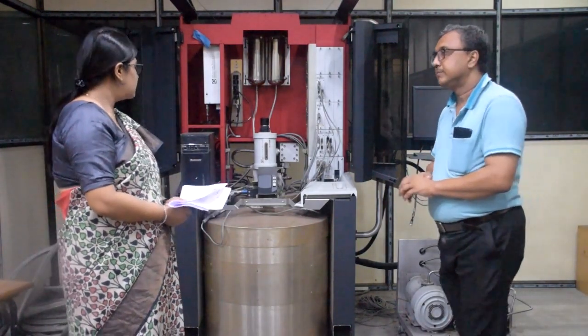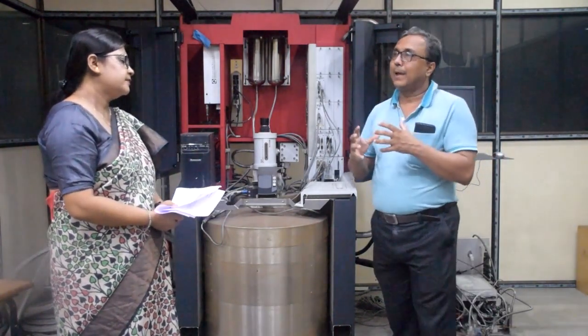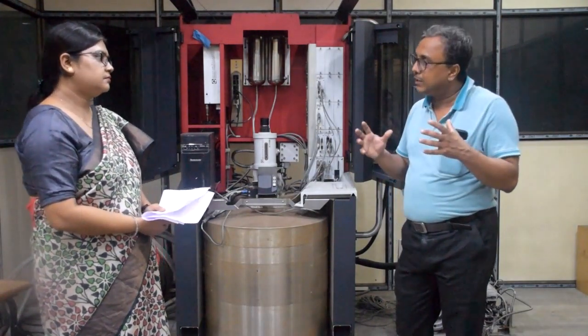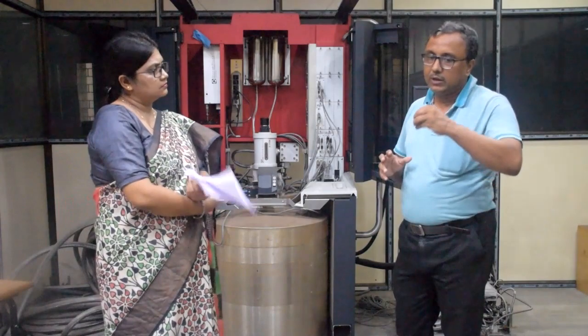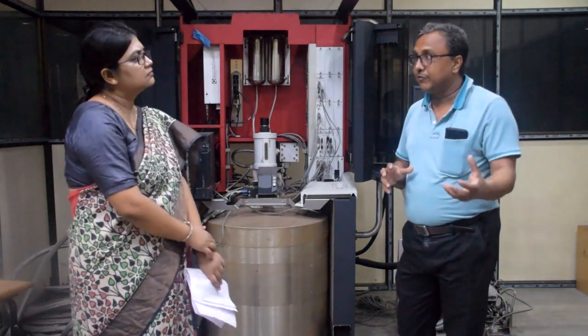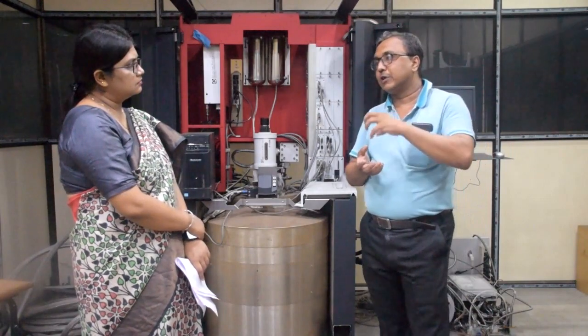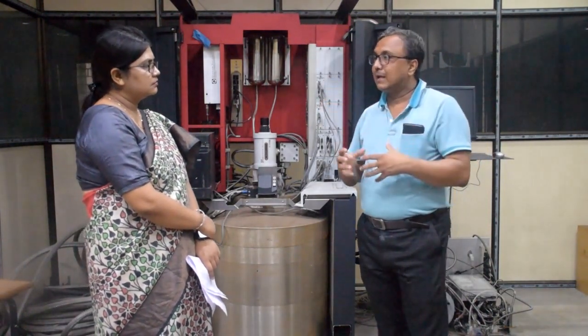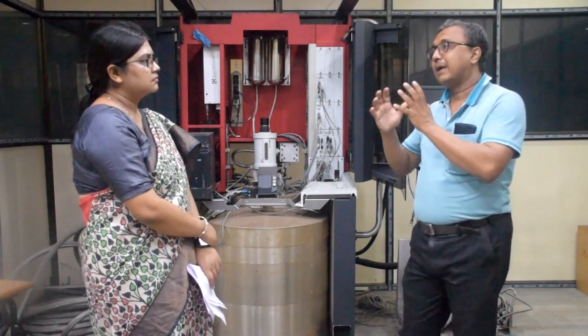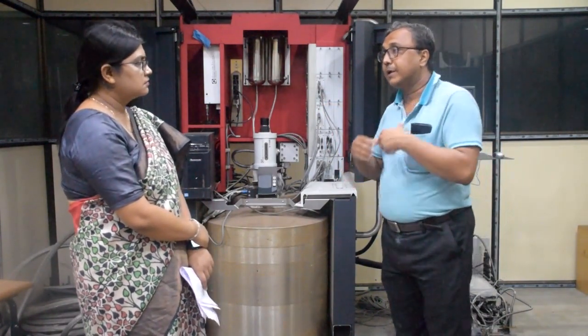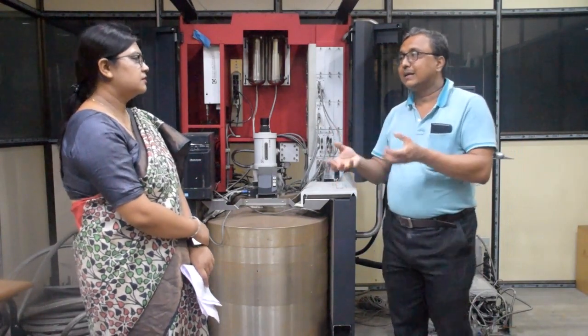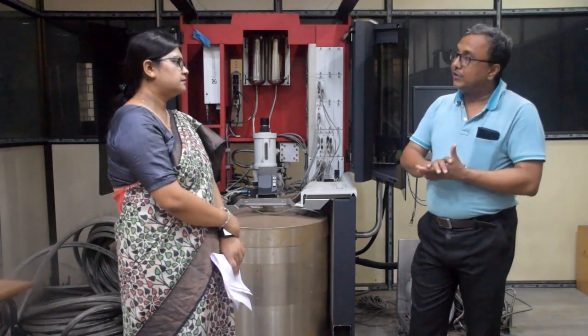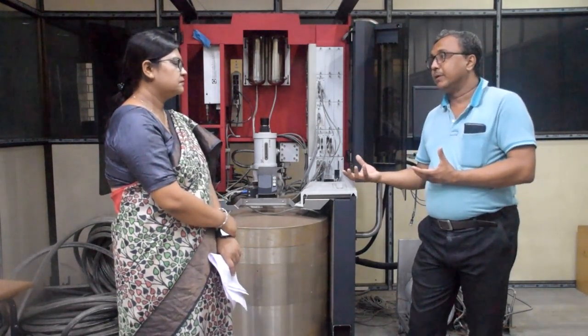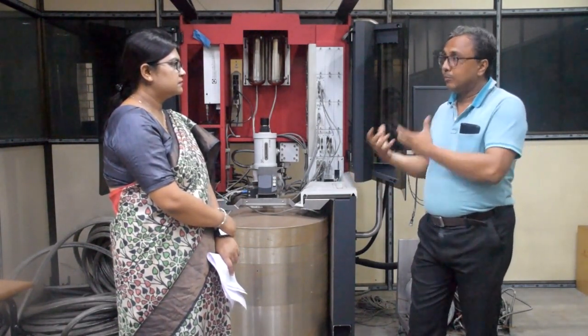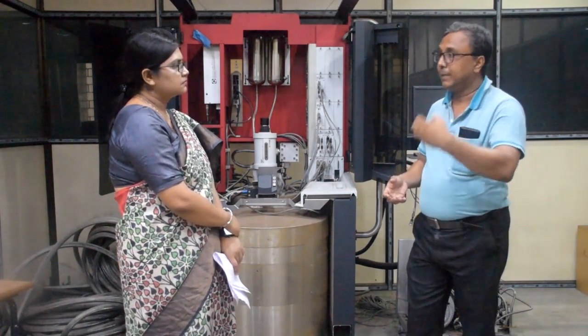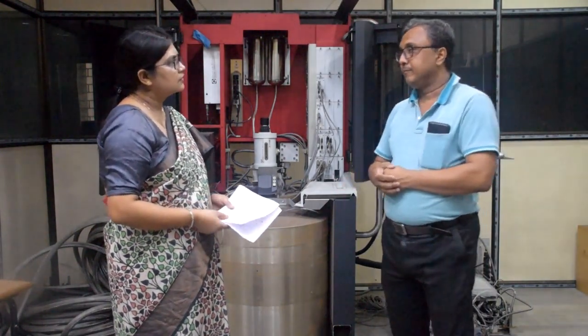Why is it significant in the research of nanoscience? Magnetic material itself shows very peculiar behavior depending on temperature, and when we transfer to nanomaterial, the surface to volume ratio gets enhanced. That means there is a huge possibility that the magnetic phase, the magnetic structure and magnetic properties of the system will change. In that case, it is a very sophisticated tool to identify the change in magnetic moment, magnetic structure and magnetization once you go from the bulk sample to nanomaterial.